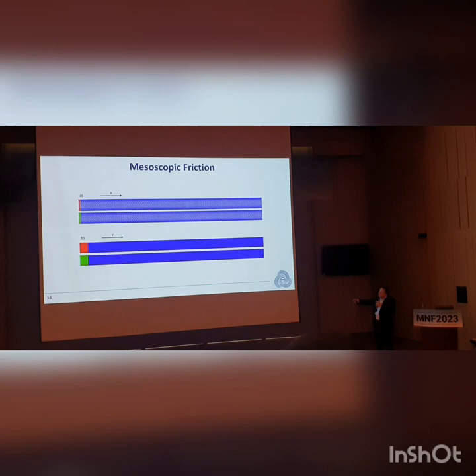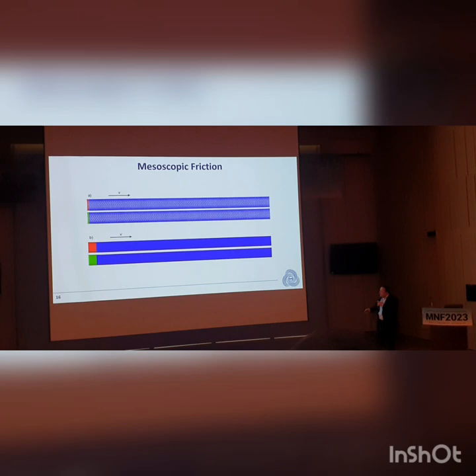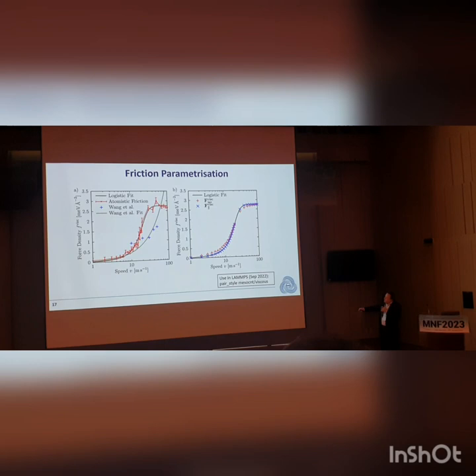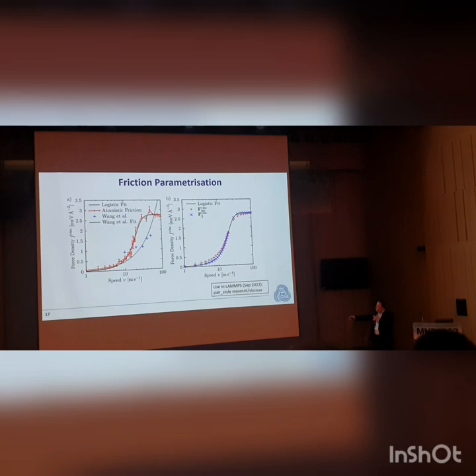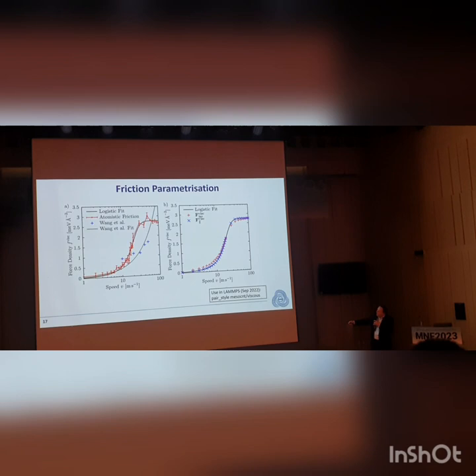One more thing needed for a good model is friction, which only really matters at the macroscopic scale. To estimate this, we take two atomic tubes, drag them across each other at a certain velocity, measure the required force, then build a potential that mimics this for our smooth coarse-grained nanotubes. The equation used is basically a logistic fit — a semi-empirical function implemented in LAMMPS as a viscous pair style force interaction. It reproduces the fact that force varies non-linearly with velocity: starting small, then increasing as you drag the tubes past each other faster.